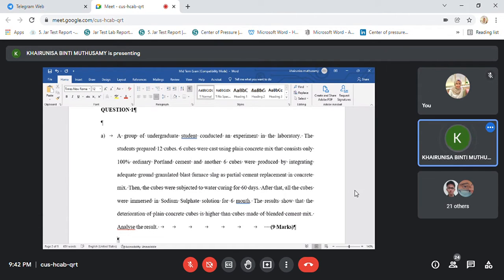Okay, what makes that blended cement concrete mix with blast furnace slag have higher resistance and higher durability than plain concrete? What could be the reason? More compact due to extra CSH gel coat. Betul lah. So in this case, the question already gives you the answer that the concrete cubes were prepared by integrating suitable, adequate content of slag.